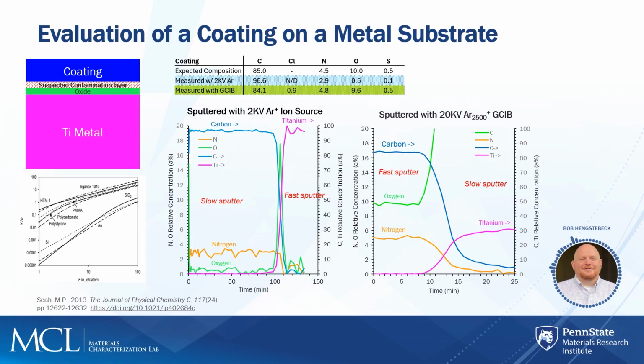Again, you might ask, why am I so excited about that? Well, that means I might have a way to very quickly clean off the organics that might be an adventitious carbon or a contaminant layer on the surface and preserve the surface that you're actually asking me to analyze and keep its chemistry. We'll take a look at what that looks like in the next slide.